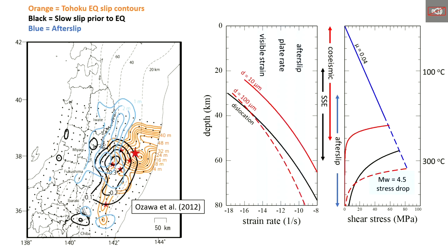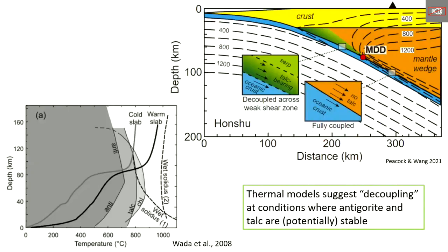And one of the things that's amazing about the Tohoku region was after the earthquake, in the year following the earthquake, there's this region of afterslip that shows like 3 meters of slip. So something happened to allow 3 meters of creep to happen over a year. And that pressure solution flow law, you can't really rule out as a mechanism that's viable for that, which is kind of cool. But why was that possible? It was only possible because it's so cold that you can get to higher stresses by having to go so deep.